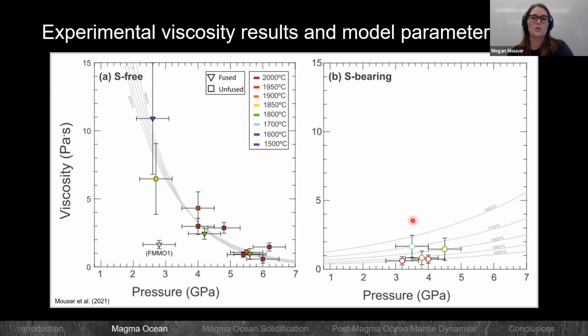Now, if we move over to the sulfur-bearing in panel B, it's a much more constrained data set, and this was certainly not for a lack of trying. We did try to explore more of the pressure-temperature space, but this was a very difficult liquid to work with. But within this limited data set, there does appear to be temperature sensitivity and probably pressure sensitivity as well. But when we look at this data at all tested PT conditions and compare it to the sulfur-free, it's lower